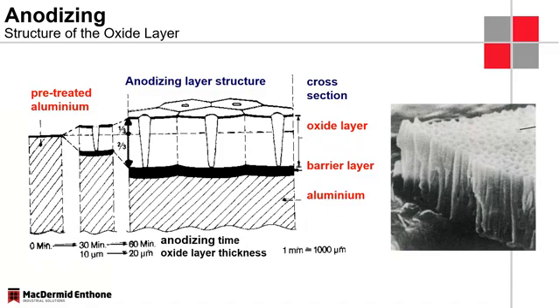This is a schematic of how an anodizing layer forms. There's always a lot of questions about how this anodized layer is actually formed, or is it an integral part of the aluminum component itself, and it really is. So this is not like the traditional electroplating where we plate and deposit another metal layer on top of the substrate. The anodized layer actually grows out of the aluminum substrate itself. We see that here quite nicely.